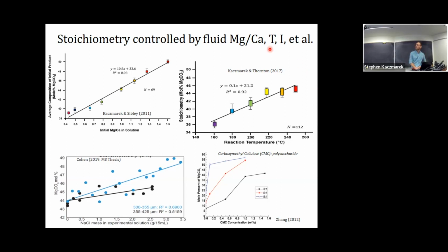Well, we went into the lab and looked at a number of key parameters. One is when you change the magnesium calcium ratio in solution, we show a positive correlation between that and the amount of magnesium in the dolomite. More magnesium in your fluids, we showed faster rates, but also the material you produce has more magnesium in it. Pretty strong relationship.